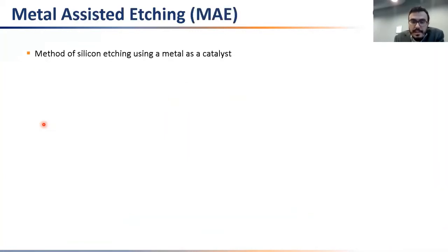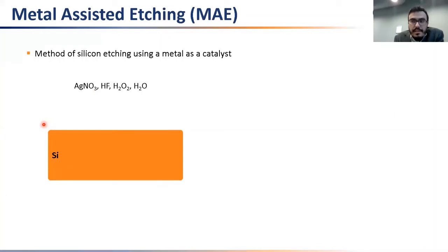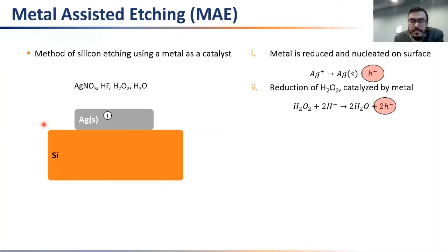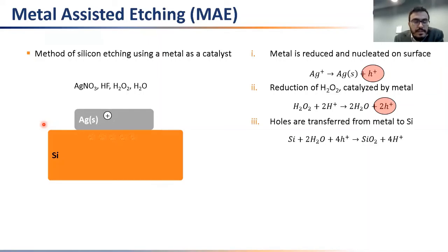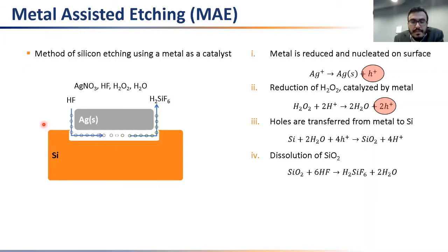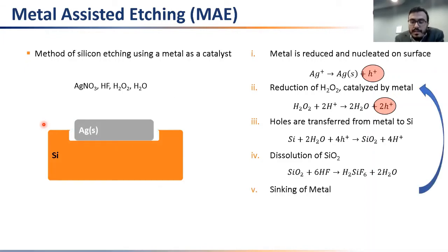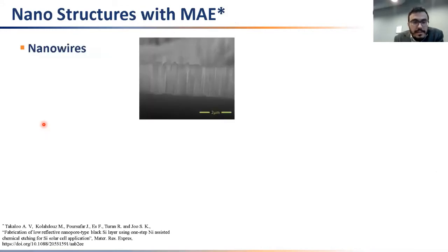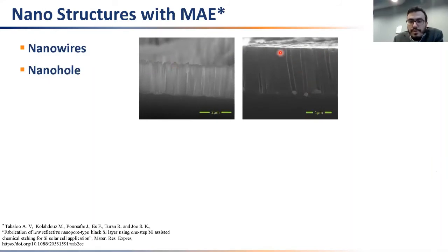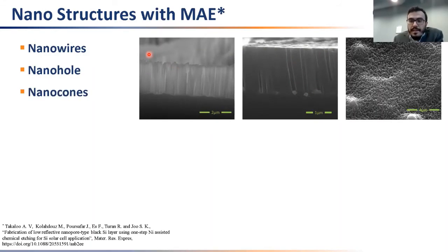And what is metal-assisted etching? Basically, it's using metal as a catalyst to etch silicon randomly, using oxidation of silicon under the silver catalysts, so that silicon is oxidized faster under the metal and etched by hydrofluoric acid, and the metal sinks. By this method, it occurs recursively, and the reaction continues. Using this method, you can make nanowires in front of your solar cells. You can see nanowires on the surface of silicon here. You can make nanoholes, nano-sized holes on the surface, and nanocones on the surface of your solar cells.